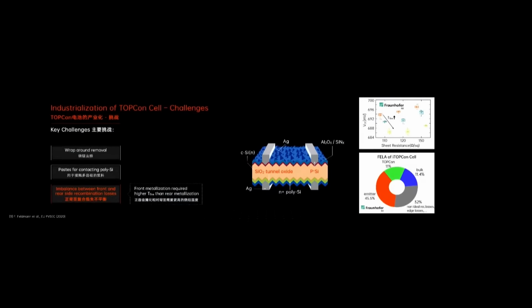side. But fortunately also a solution was found for this, and with now laser-induced fired contacts, which are fired at the end of the process sequence, we can really minimize contact recombination at the front metal contacts as well.